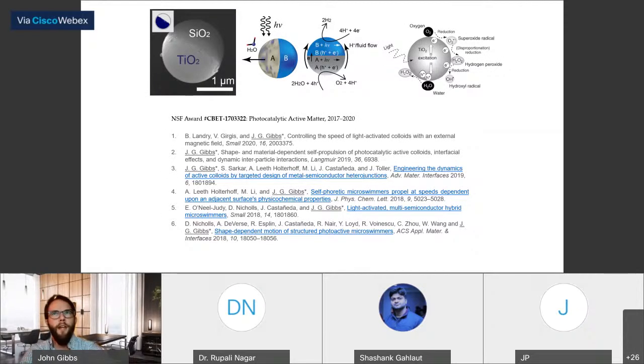The first thing we wanted to look at was actually done by Peer Fischer's group beforehand, so they came to this idea before we did: taking TiO2 and putting it onto an SiO2 underlayer. The top left is an SEM image that shows TiO2 distributed on half of a spherical particle of silicon dioxide. Because of the difference in the two phases, we have one active side and one inert phase. Then there's a complicated chemical reaction and phoretic behavior that leads to the self-propulsion of the particles.